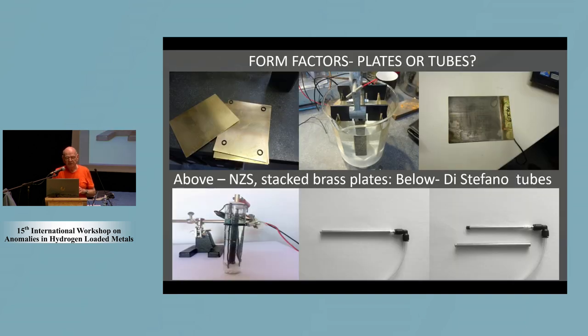And here you see some comments about the form factor. So top left are the kind of brass plates that I was using. I started out doing co-deposition, as Frank said was necessary, of iron and hydrogen. In other words, simultaneously creating hydrogen at the cathode surface and plating iron onto it. Because, as has been known for several hundred years, iron absorbs a lot of hydrogen. In fact, it may in some ways be better than palladium. Not such a nice material to work with.